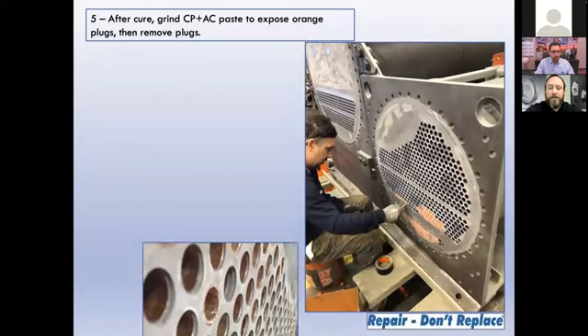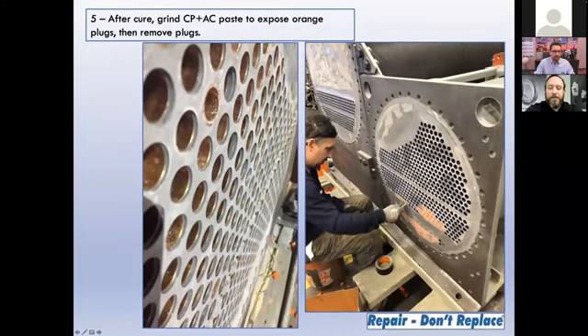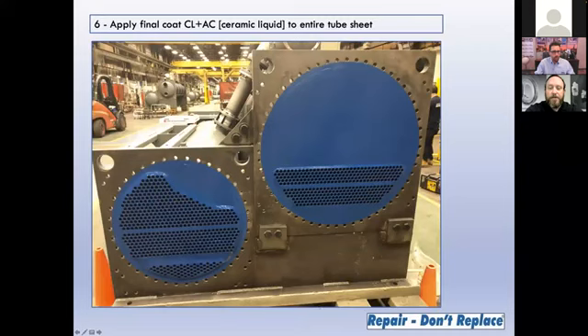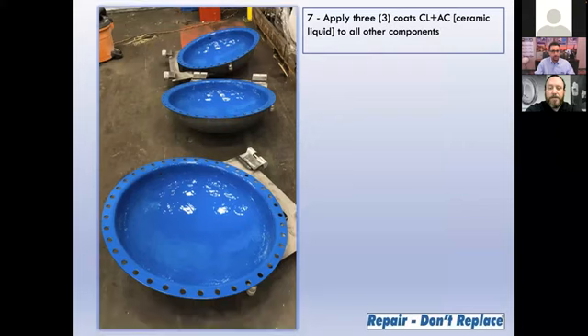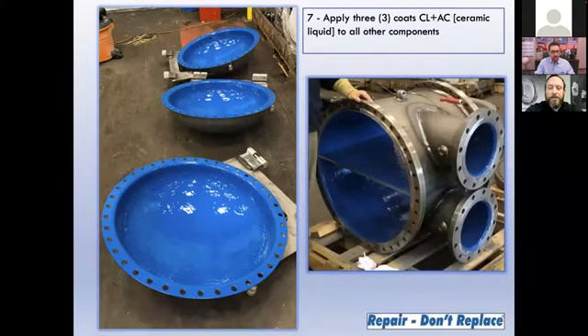Once all of the plugs are removed, this is the type of finish that we're looking for. Smooth, monolithic finish, and no gaps between the CP plus AC and the copper tubes. This would be the final thing we do for the chillers. We would apply one final coat of Ceramaloy CL plus AC to the tube sheets, and we apply 3 coats of the Ceramaloy CL plus AC to the dish return heads and water boxes.